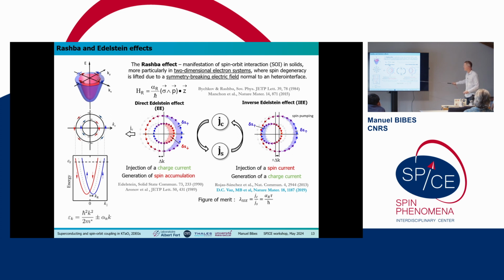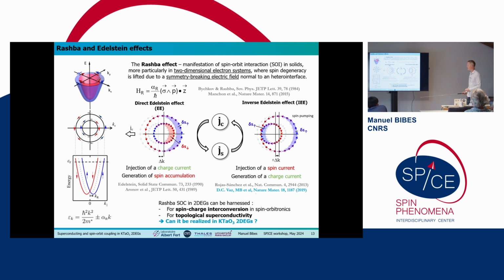And there's a figure of merit for this, but I don't want to go into the details. To have an efficient conversion, you need a large Rashba spin-orbit coupling and also a large relaxation time. So this is very interesting for us working in spintronics because you can do charge to spin and spin to charge conversion, meaning you can generate spins from a non-magnetic material and detect spins in non-magnetic materials. So you could in principle do spintronics getting rid completely of the ferromagnets, which has a number of advantages.